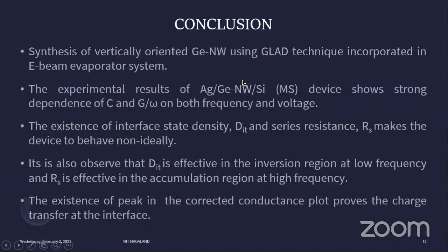In conclusion, we were able to synthesize germanium nanowires using the GLAD technique in an E-beam evaporator, and we conclude that this device is dependent on both frequency and voltage. Also, the presence of DIT and series resistance is established, and DIT is effective in the inversion region at low frequency and series resistance at high frequency in the accumulation region. Also, the peak in the corrected conductance infers that there is a charge transfer at the interface.